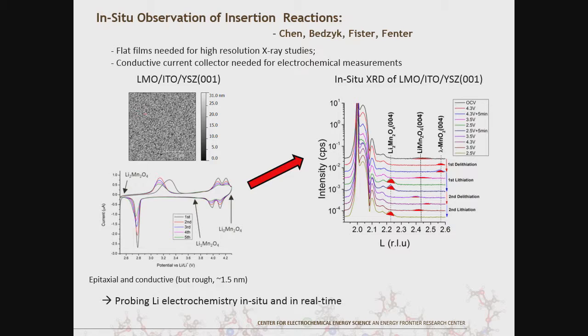Nevertheless, because it's a conductive layer, we can do electrochemistry, and you can see we're going all the way from 4 volts down to 3 volts, so we're putting 2 lithium in and pulling it back out. This is X-ray diffraction from this in situ during the process, and this little red peak here as it's going back and forth is the lithiation, delithiation of the LMO. So this is essentially bulk diffraction of oriented particles.